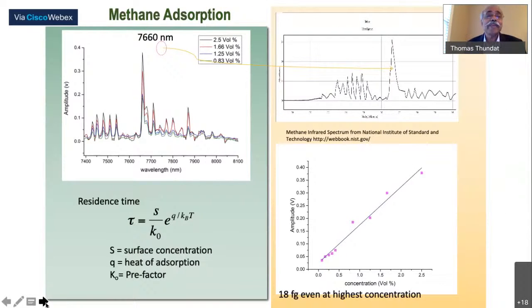And you can even detect methane. Methane, for example, CH4, is totally inert. It doesn't even adsorb on surfaces, but they have some residence time because they have some adsorption energy, and that is around nanoseconds. So they may stay on the surface for a nanosecond. And if you are exposing to, say, 1% volume percentage of methane, at any moment in time, there are some molecules out there adsorbing and desorbing, and we can see the spectrum. And we found that it is around 18 femtograms of methane adsorbed that is giving out the signal, actually.